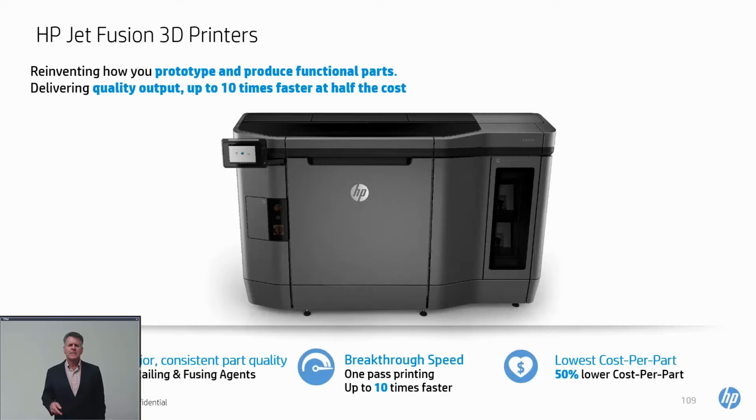All right, I hope you guys were able to watch that. Like I said, go to YouTube and look at HP 3D printing and you'll see a bit more details and some other things. What they didn't really point out in that video is each layer is 6 to 12 seconds. I just use 10 seconds because it's easier on the math. But it's 10 seconds a layer regardless of what's on the layer. So if you've got 40 sets of sunglasses on there, it's still 10 seconds a layer. If you've got one part, it's still 10 seconds a layer. But it adds up to about 2 inches per hour build speed.